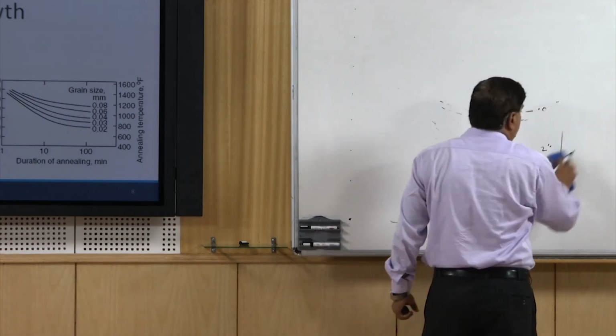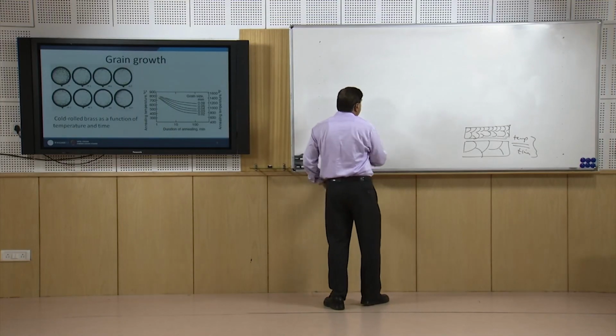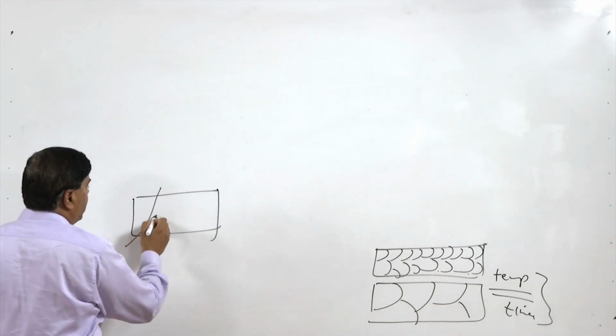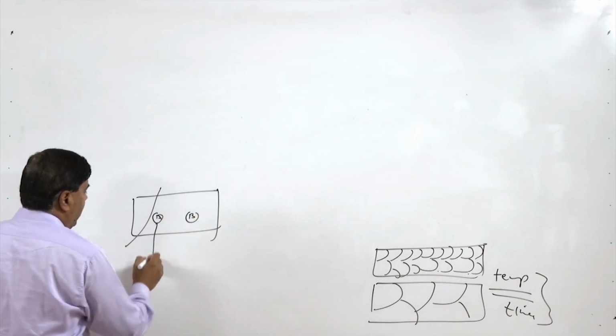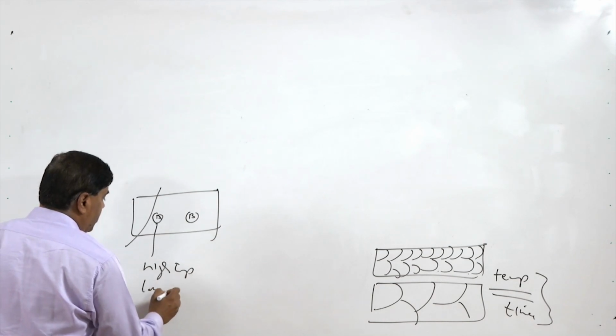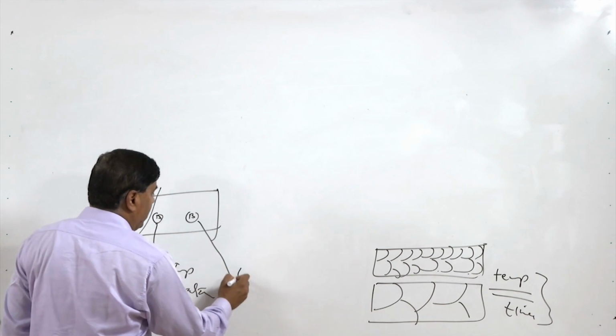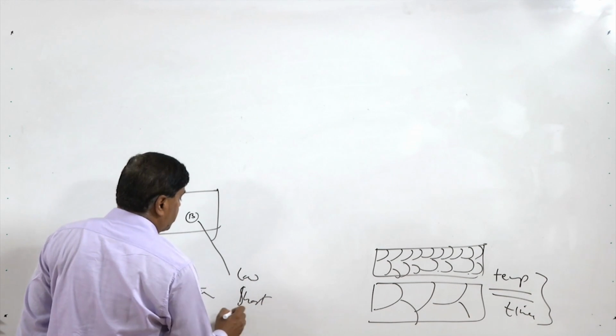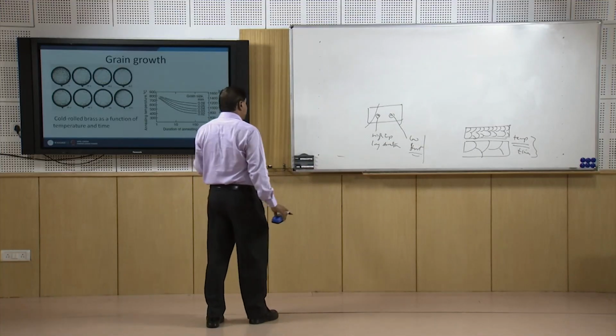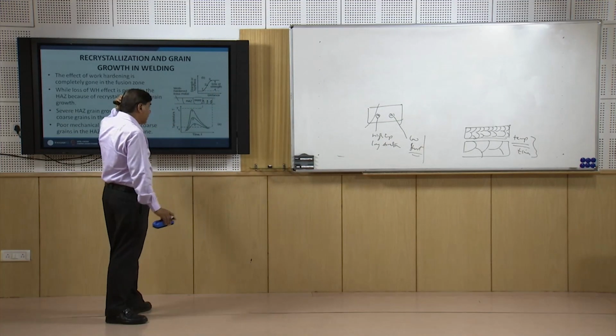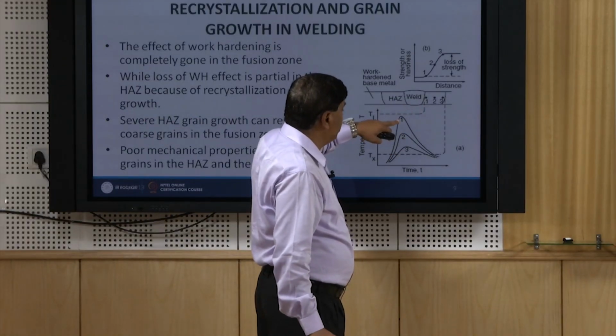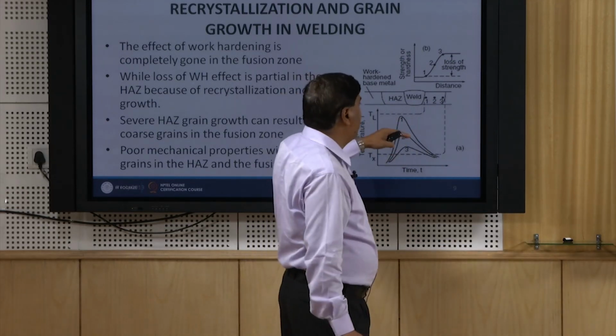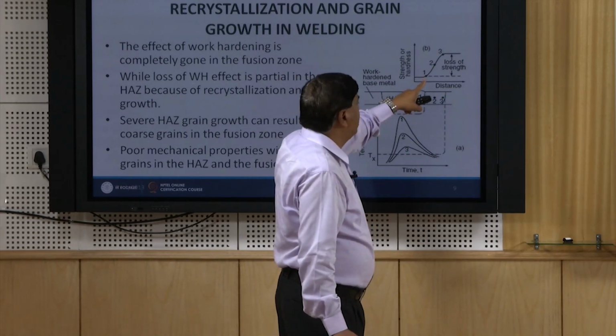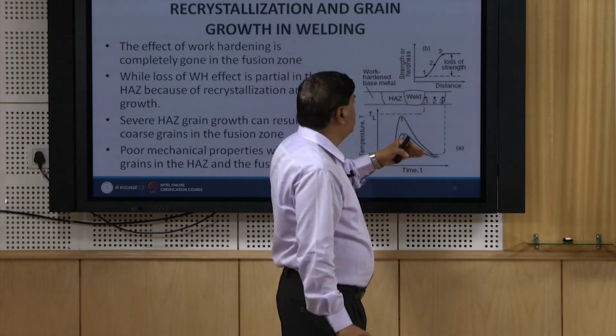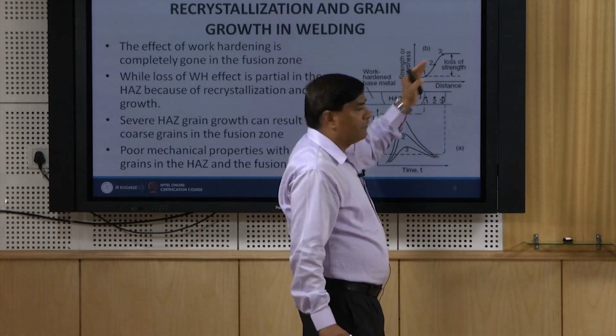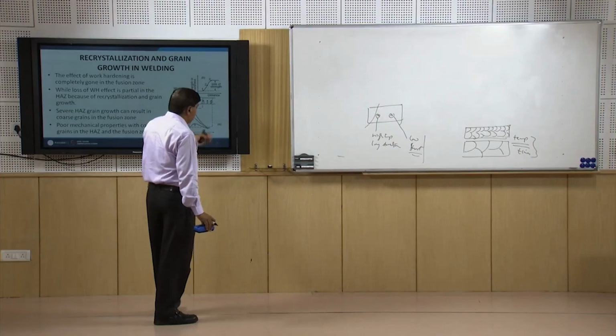Now we have to relate this with the weld joints. We know that the points close to the fusion boundary, like say A and B, will have a higher temperature. A will have high temperature and long duration at high temperature, as we have seen from the weld thermal cycle, while B has low temperature and short high temperature exposure. So, this is just the opposite, and this in turn will be reflected in the weld thermal cycle. This is the effect of the weld thermal cycle. When the point is very close to the fusion boundary, the peak temperature is high, and the duration for which high temperature exposure is given is also long as compared to points 2 and 3. Accordingly, we will see that the loss of strength due to recrystallization and grain growth is maximum at point 1, and then the loss of strength and hardness will keep on decreasing as the distance from the fusion boundary increases.